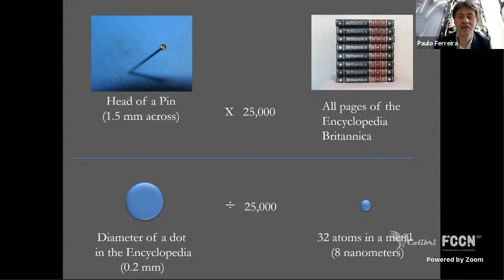So we can now do reverse engineering. We take the diameter of a dot in the encyclopedia, that's about 0.2 millimeters. You divide by the 25,000 times, and you get about 8 nanometers. In terms of atomic scale, that means about 32 atoms side by side. So this exercise basically tells us that if I can write the dot of a period of the encyclopedia with 32 atoms, I can actually insert the 24 volumes of the encyclopedia on the head of the pin.